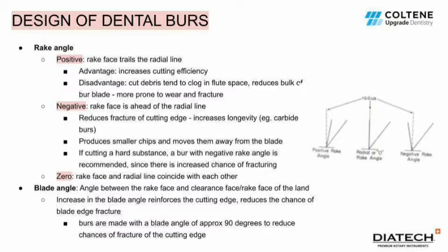Lastly, in burrs with a 0 rake angle, the rake face and radial line coincide with each other. The blade angle is the angle between the rake face and the clearance face of the land. An increase in the blade angle reinforces the cutting edge and reduces the chance of blade edge fracture. Burrs made with a blade angle of approximately 90 degrees reduce the chances of fracture of the cutting edge.